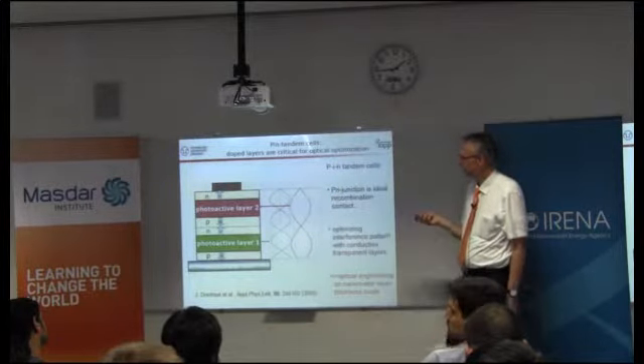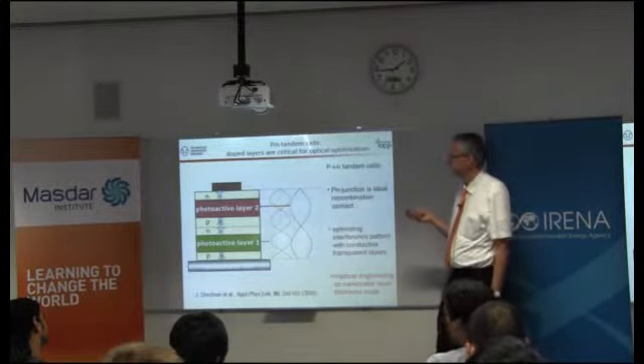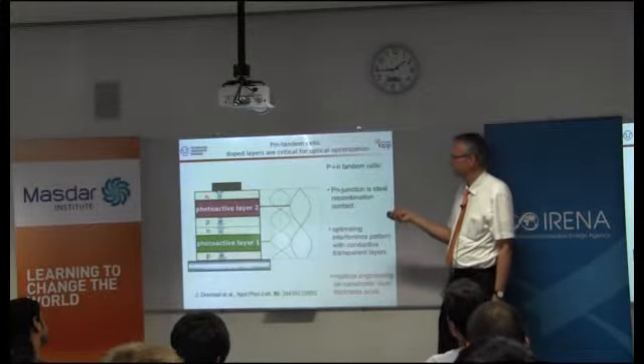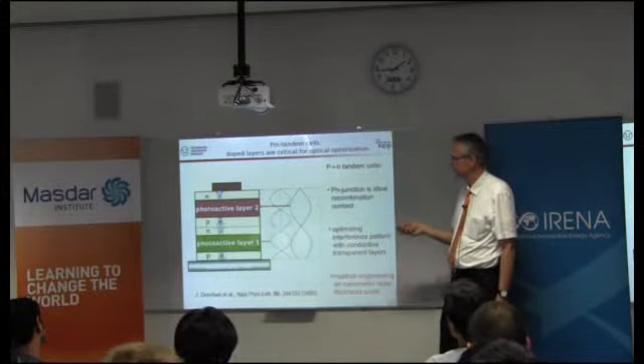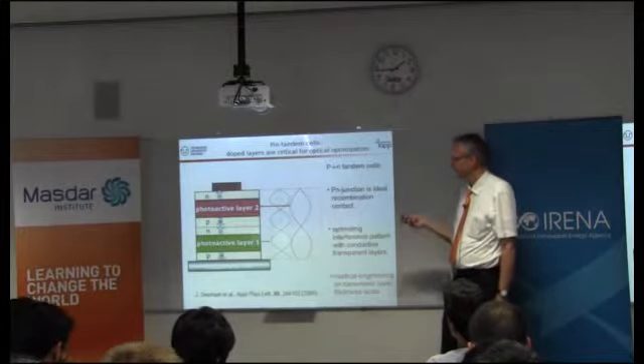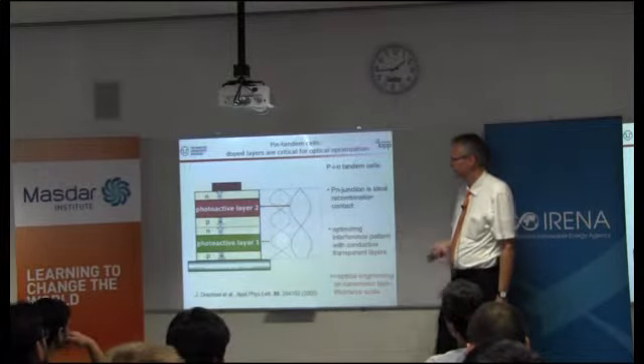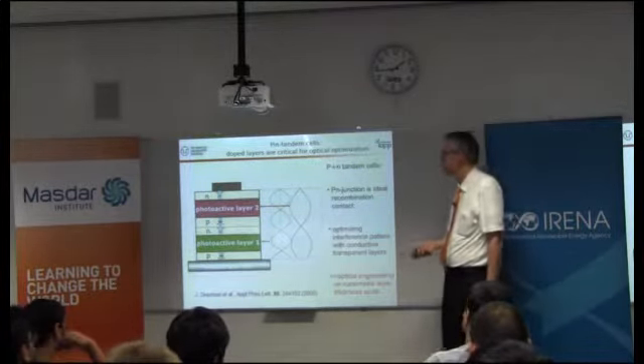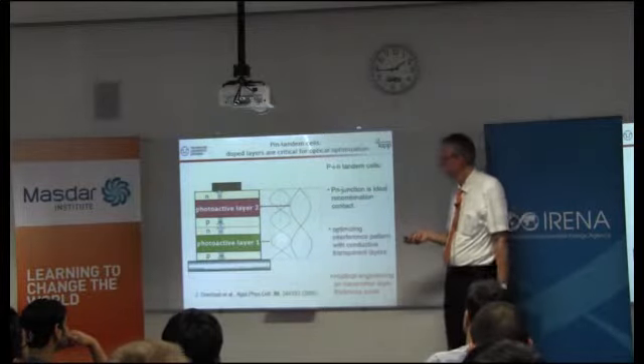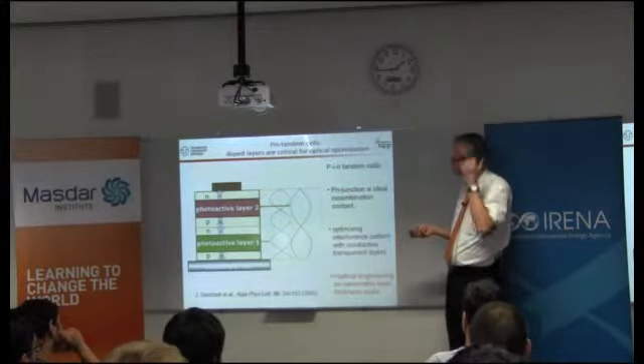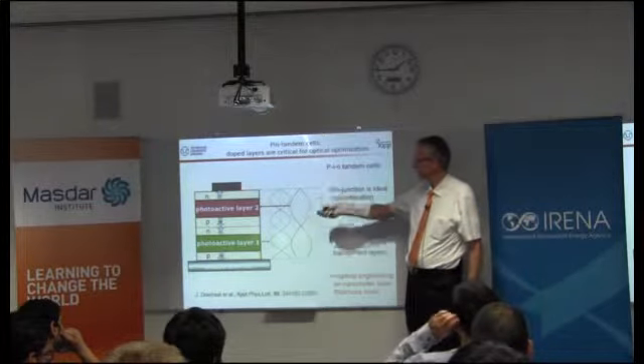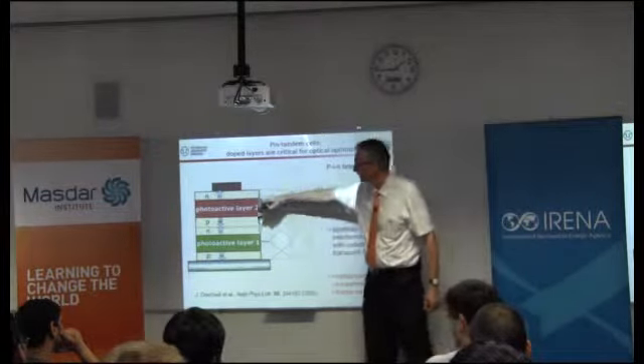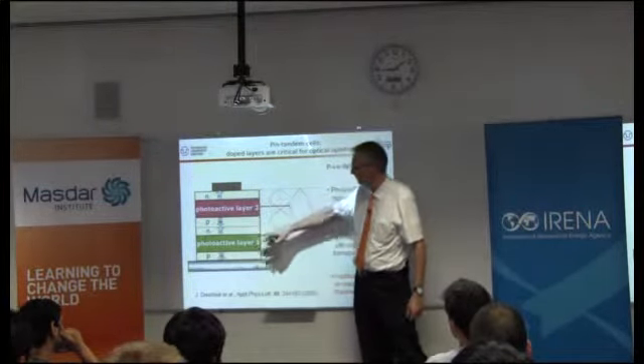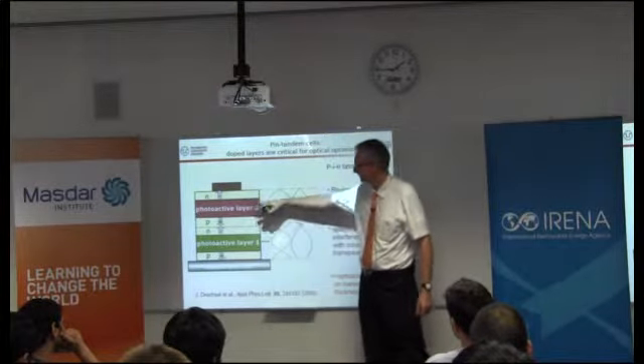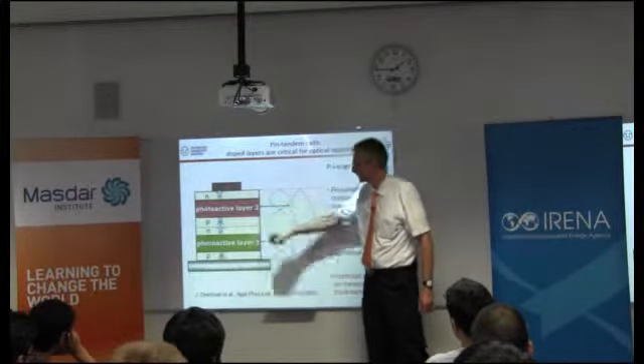And fortunately, we have developed years ago a technology which allows that very nicely. We have developed these N-type and P-type doped organics. In the Samsung phone, actually a P-type doped layer is contained. That is why Samsung is using Novaled technology. But here in the solar cell, it has two advantages. The one point is these layers are transparent, so you can move the absorber layer to the point where you have the highest field intensity by these transparent window layers.